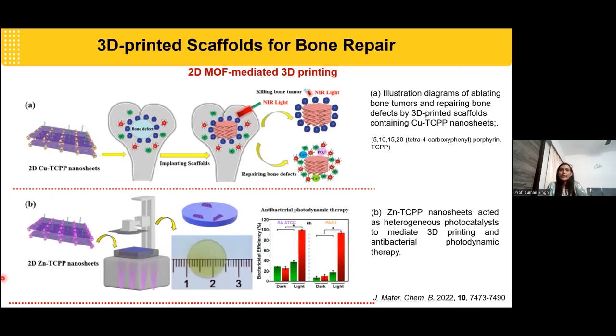So this 3D printing has made it possible that bone repairs can also be done using some 3D printed scaffolds. Here in this example, the authors have used copper based metal organic framework in the form of sheets, and they have impregnated this bone structure and studied the bone repair. And if we see the B part, this has multiple applications where they have used it for heterogeneous photocatalysis as well as for biomedical applications. So, next please.